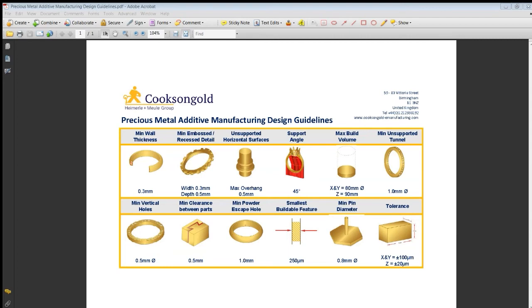This can also go up to 100 millimeters in diameter if we go on the M100s. And the Z-axis, so how tall it can be, is 90 millimeters. What I would say to this is people in the past have sent us parts that are exactly 90 millimeters tall, but don't take into account that we actually have to add on a support structure underneath. So then it becomes too tall to be built. So if you are sending something through, I would probably try and work to 85 millimeters.